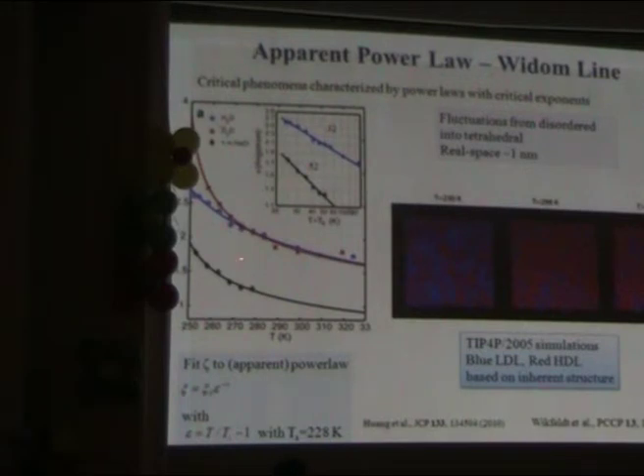Here are the data for H2O, for D2O, and for a 1 molar solution of sodium chloride. We can fit an apparent power law to the correlation length, where we use the temperature 228 Kelvin, similar to the isothermal compressibility and CP.